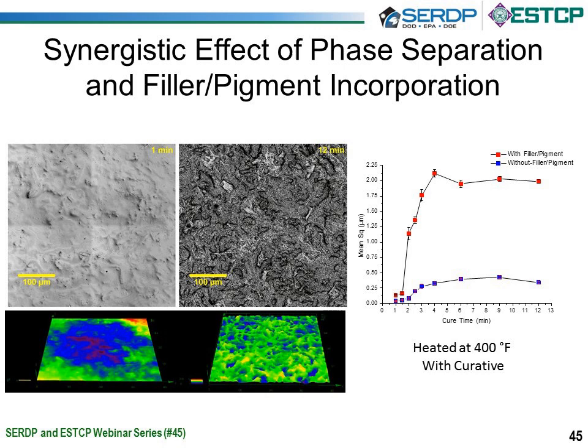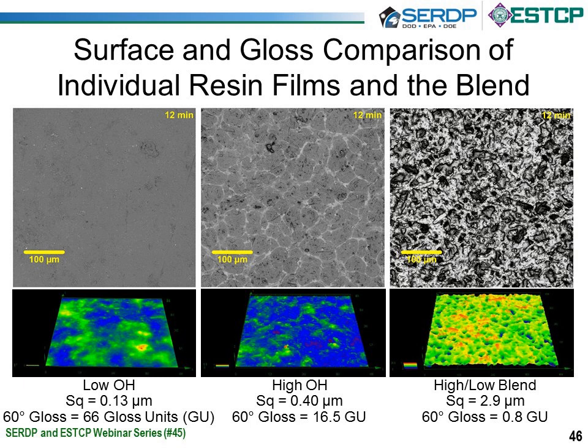Slide 46 is how do we quantify the effects, although we can visualize these and look at the roughness. Starting with the left side, we have the low hydroxyl, the low OH polyol being cross-linked, low hydroxyl only, no blends, with the pigments. And you can see on the very left side, the root mean square of 0.13 micron, so a relatively smooth surface, and with 66 gloss units, which really confirms that it's a very high gloss system. In the center is a high OH polyol that is cross-linked. As you can see, it's slightly more roughness with the numbers at the bottom, 0.4 microns, and we're down to 16.5 gloss units at 60 degrees.